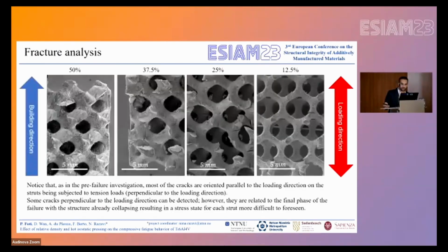If we look at the fracture analysis with the different relative densities, we can also notice some cracks that are oriented perpendicular to the loading direction. However, these should be attributed to the final phase of the failure, in which the structure is already collapsing and it results in a stress state that is much more difficult to foresee.